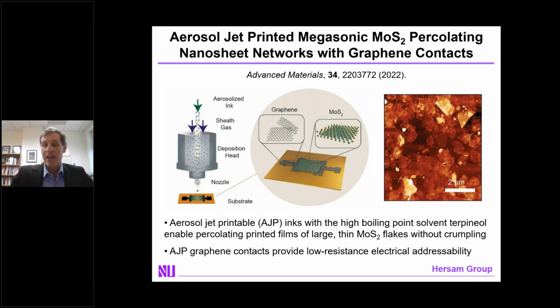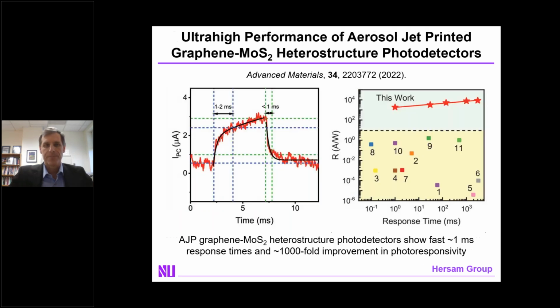One challenge that we have here is that when the flakes are single layer thickness and micron in size, if you don't control the evaporation of the solvent carefully, you get crumpling of the molybdenum disulfide, which is suboptimal for charge transport and therefore photodetection. But by incorporating a small amount of high boiling point solvent, we can control that drying process. This gives us nice, large, thin molybdenum disulfide flakes, forming percolating networks without crumpling. And then if we use graphene contacts, we can achieve low resistance electrical addressability.